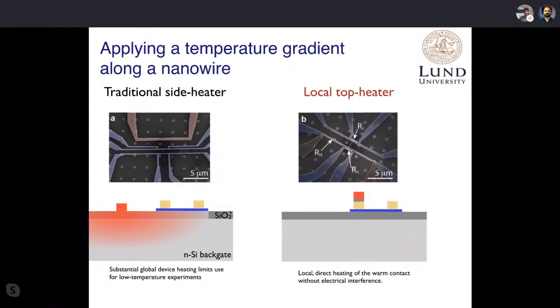So an important breakthrough was that in our group, Jan Gluschke, a master student at the time, developed a system where we put the heater not next to the nanowire, but on top of the ohmic contacts. So again, there's a nanowire here. You have 2 sets of contacts. Both of them allow for 4-point measurements. Then you put on top of the contacts an oxide layer, to electrically insulate, and then you put another circuit straight on top. So if I heat now, I heat very locally the ohmic contact and thereby the electrons in the metal, which then will heat the electrons in the nanowire very locally.